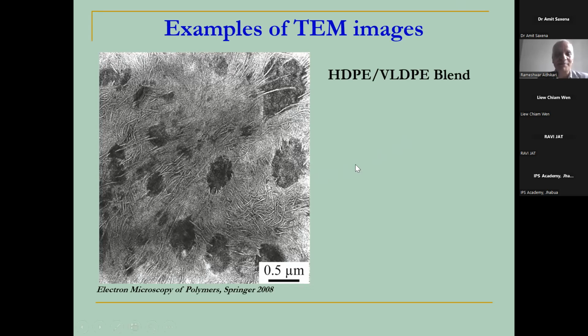This is an example of the transmission electron micrograph of a mixture of high density polyethylene and very low density polyethylene. I don't want to elaborate why they are so called, but mainly, high density polyethylenes have much linear structures in the chain. And very low density polyethylene or low density polyethylenes have some branched structures that makes a kind of hindrance in the crystallization behavior.